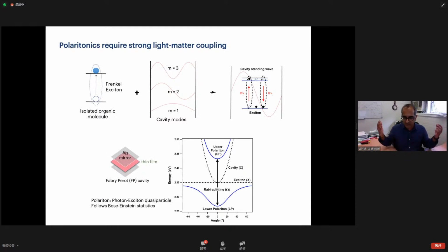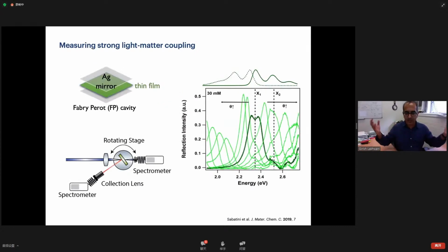Once you split energy levels, effectively you have changed the potential energy surface of the material without changing the material itself. What that gives you is a big handle on changing or driving different photophysics and different material properties altogether. One example is if you pick up a material and put it in a cavity, you can see the absorption starts splitting and you can split the peaks. That's how you can show that you've indeed achieved strong light-matter coupling.